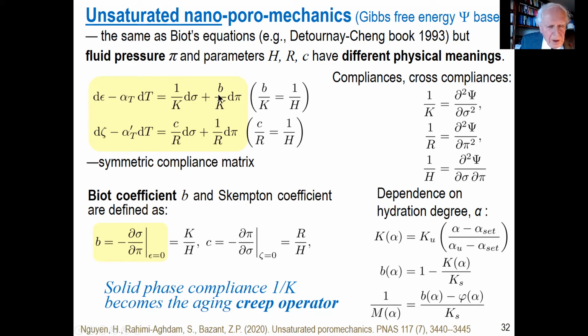And of course, this equation, because all must fit the Gibbs free energy, must give symmetric equation systems. So B over K, C over R must be equal as expressed here. And here B is the famous Biot coefficient, which gives us the change of volumetric stress in the solid due to unit change of equivalent pore pressure and no change of strain. So that's one parameter, and a Skempton parameter here, but this is the most important one. It occurs in all kinds of calculations.